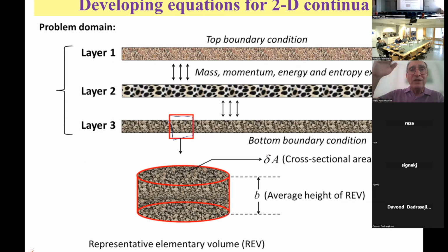So we don't have REV moving over the thickness. There's one REV over the thickness, and then of course, many REVs laterally, which means that when you do the averaging, you don't get three-dimensional equations, you only get two-dimensional equations. But you get one set of equations for layer 1, two-dimensional, one set of equations for layer 2, one set of equations for layer 3, and then they exchange with each other mass, momentum, energy, and entropy, and so on.